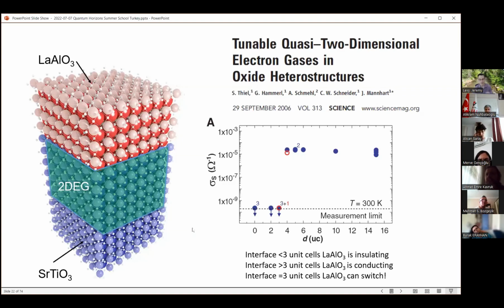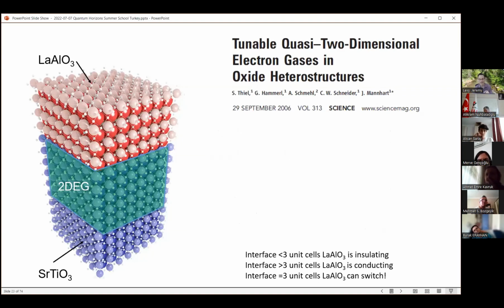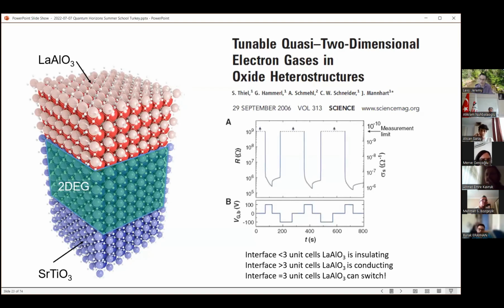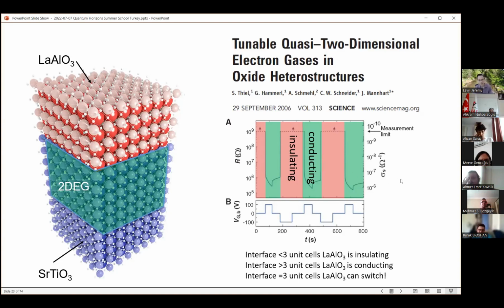Then if you took that 3 unit cell sample and applied a voltage to the back of the substrate, you could switch the interface between the conducting and insulating state. If you put 100 volts across the back of this substrate, this 100-volt pulse would switch the interface to a conductive state, and it would remain conducting when you turn off the voltage. If you wanted to switch it back to the insulating state, you just change the sign of the voltage, and it becomes an insulator. This, to me, was actually one of the... It wasn't like figure 1. It was figure 3 or 4.